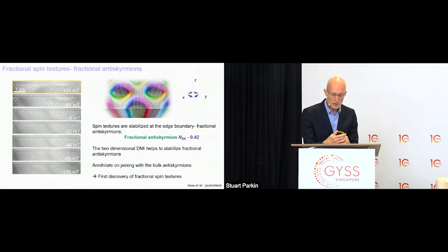And I just wanted to briefly mention that recently we've discovered an even more interesting object, fractional anti-skyrmions at the edges of these lamella. This hadn't been theoretically predicted, but we believe this is a consequence of the interior structure through a bulk-boundary correspondence. These fractional anti-skyrmions only appear at the edges, and this has been confirmed theoretically by our collaborators at the University of Basel and the group of Daniel Loss. This work is not yet published, and so I'm going to skip this.